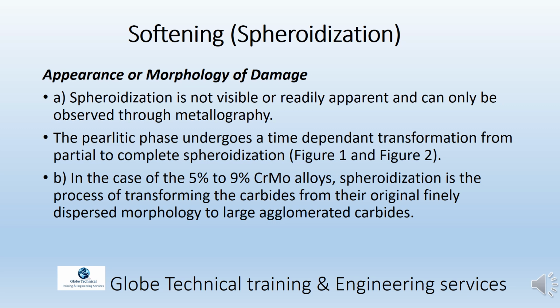Appearance or morphology of damage. A. Spheroidization is not visible or readily apparent and can only be observed through metallography. The pearlitic phase undergoes a time-dependent transformation from partial to complete spheroidization, Figure 1 and Figure 2. B. In the case of the 5% to 9% Cr-Mo alloys, spheroidization is the process of transforming the carbides from their original finely dispersed morphology to large agglomerated carbides.